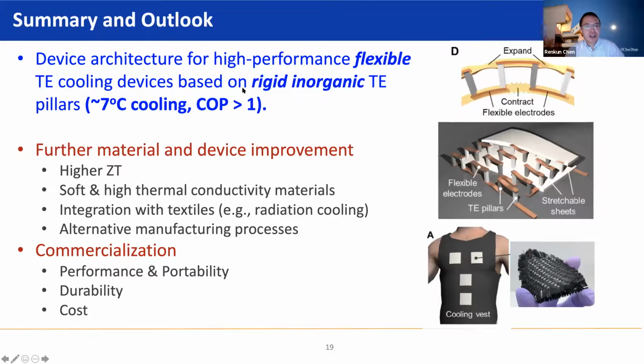So to summarize, we think it's possible to use high performance rigid inorganic thermoelectric material to create flexible thermoelectric devices for cooling and heating. And the key is to design the device. And there are many other aspects that we still need to work on to really make this device commercially viable. So from materials and device point of view, it's always good to have higher ZT, and we also want to have a better elastomer material that's soft and also with high thermal conductivity. And maybe we want to integrate it with textile, for example, infrared-transparent textile for radiative cooling. And there are also possible alternative manufacturing processes that will make this device much thinner and lighter.